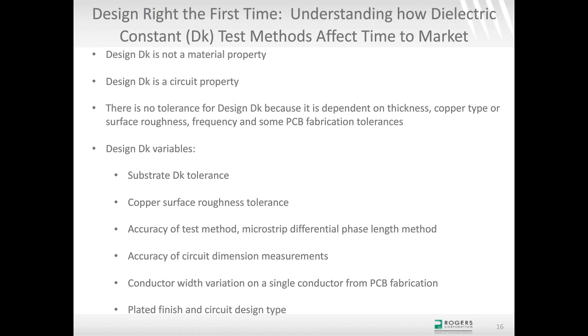But what design Dk is, it's not a material property. It's actually a circuit property. And what I mean by that, a material property like CTE, coefficient of thermal expansion, the material is going to expand and contract a certain amount due to the CTE when the material is heated and cooled. That's a property of the material only. But design Dk is not a property of the material only. There's actually circuit influences. There are several different influences, circuit fabrication, design. So it's actually a circuit property.